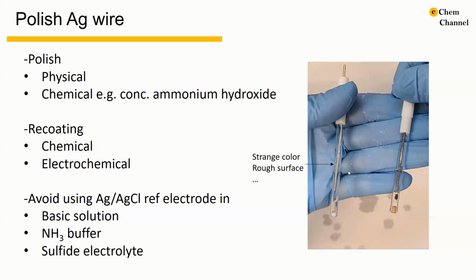For regular using of the silver-silver chloride reference electrode, we should always avoid basic solution. That is because the silver can form silver oxide or silver hydroxide with the basic solution. And we should also avoid using the ammonia buffer. That is because the ammonia can dissolve the silver chloride. We should also avoid using the sulfide electrolyte. That is because silver sulfide is insoluble.